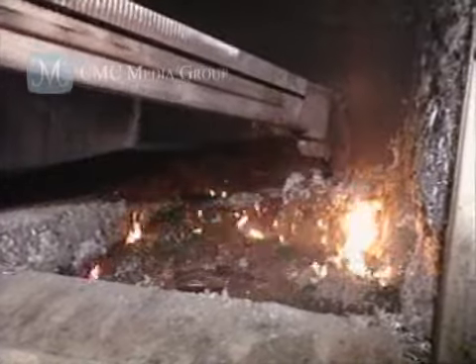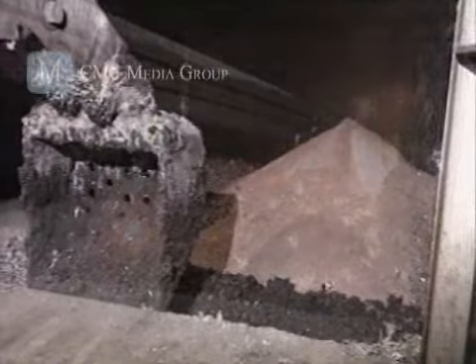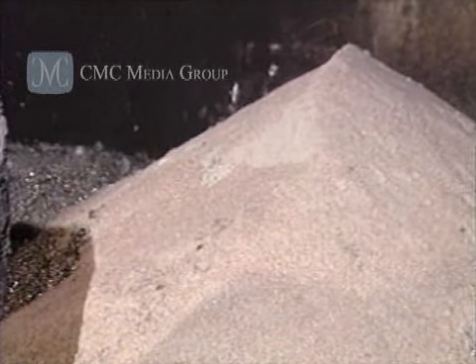Dross is black with good metal separation, which means that the aluminum content in the dross can be recovered at the hammer mill. Did you notice that the big difference between the right way and the wrong way comes down to 2 things? Working the scrap immediately and adding the flux. Don't forget, it's just as easy to do it right as it is to do it wrong.